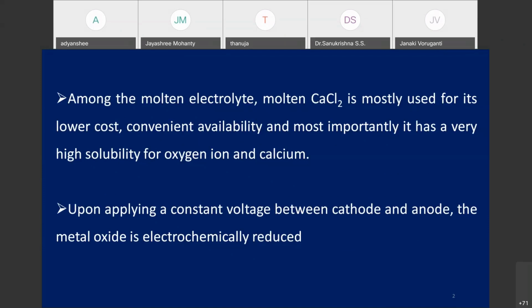Calcium chloride is not a harmful reagent. Sodium chloride also. They are not that environmentally hazardous. They are also soluble in water, so their cost is low, and they are conveniently available. Another very important part is that calcium chloride has high solubility for oxygen, so that during the reduction, whatever oxygen is produced can be dissolved in calcium chloride, and again it reacts with the carbon anode to produce CO or CO2. That is why we prefer calcium chloride as the electrolyte, and this is the most significant prospect of this electrochemical process.